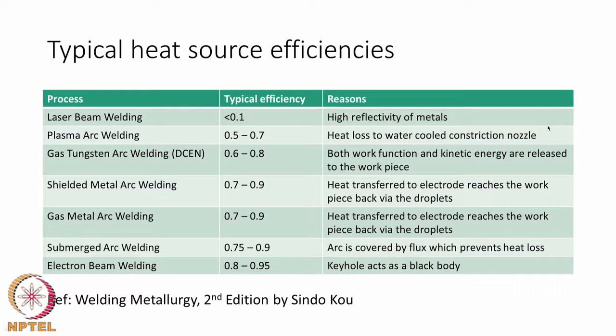So, here is a summary of the heat source efficiencies including laser and arc, and these are organized from lowest to the highest efficiency values that we have found in the literature. These are available with a lot of discussion in the book by Sindo Kou, and I am presenting here a summary. So, laser beam welding, as we have just now seen, has an efficiency much less than 10%, and the reason is the high reflectivity of the metallic materials.